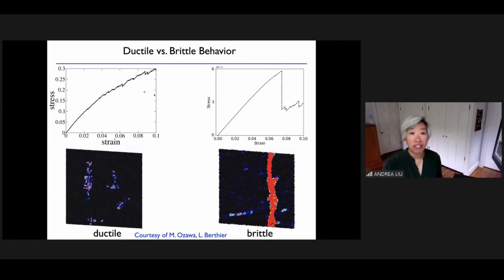Now, if you have a ductile system, you have that stress strain curve that I showed you earlier. This is just showing them over the same strain range, so the ductile one will flatten out. But the brittle one will show something like this. You can do this as an ensemble average, and you will actually see large stress drops. Not always at the same place, but you'll see this very large stress drop.